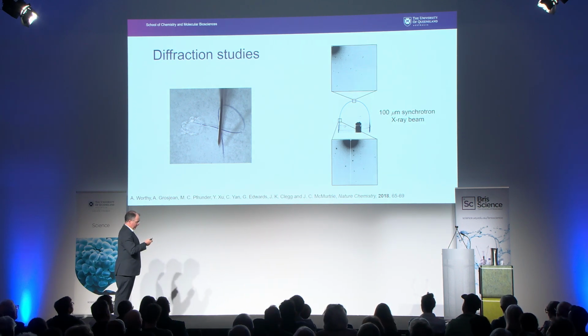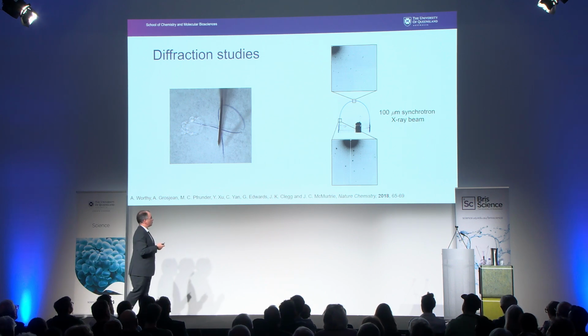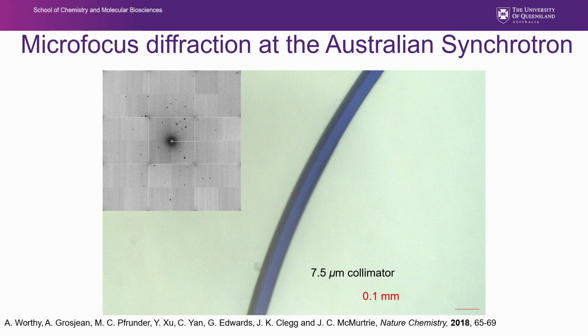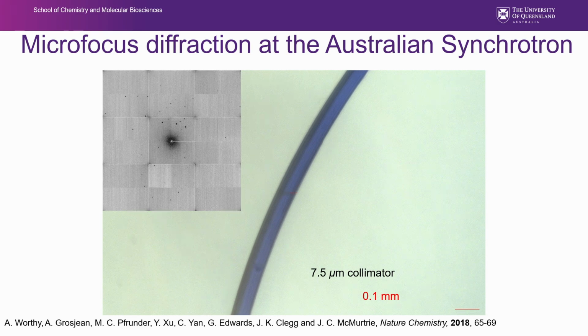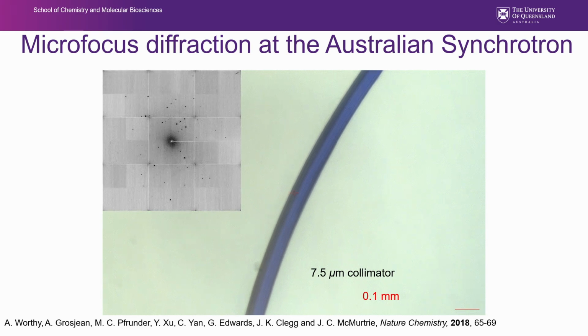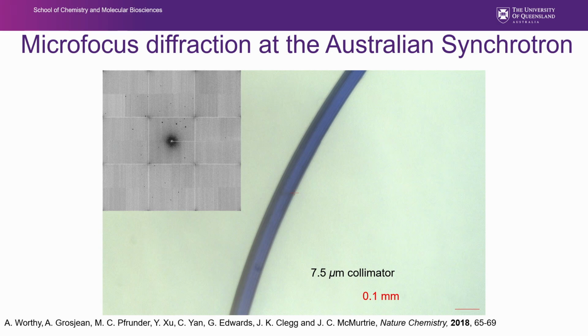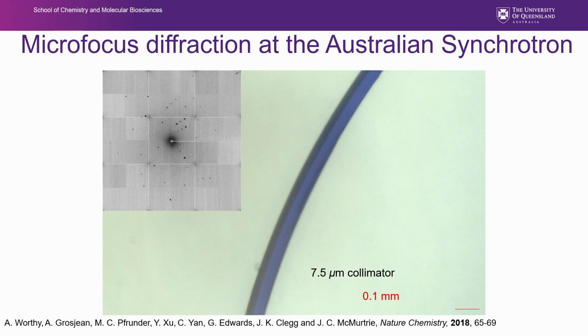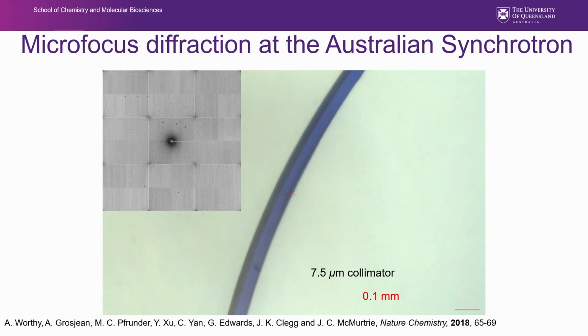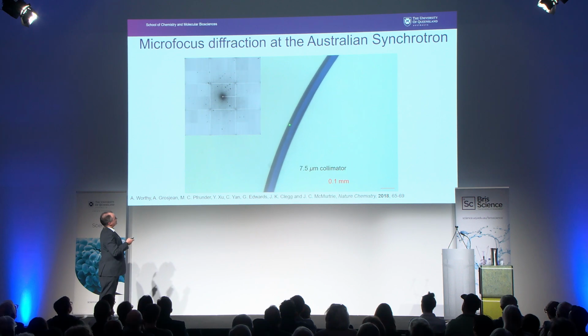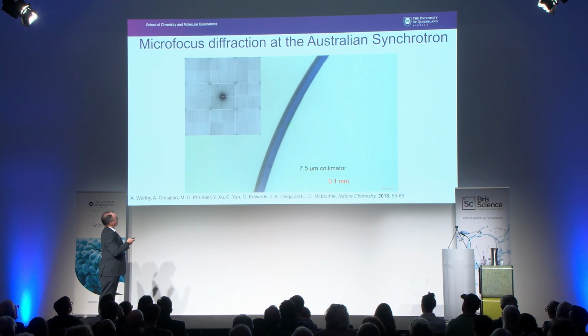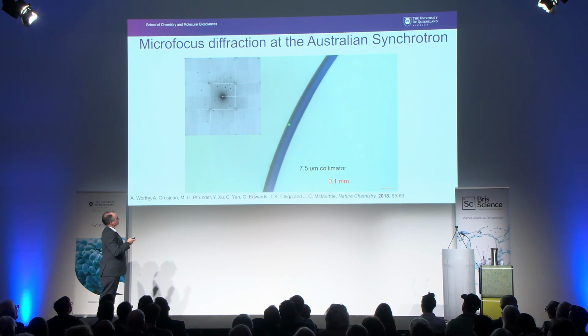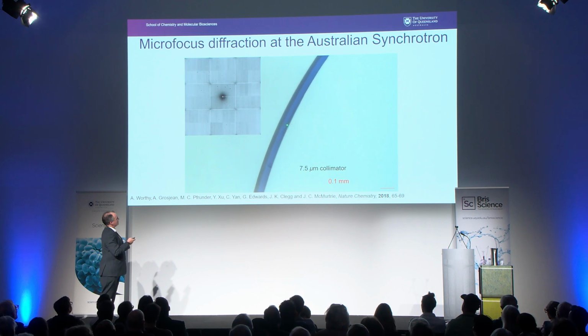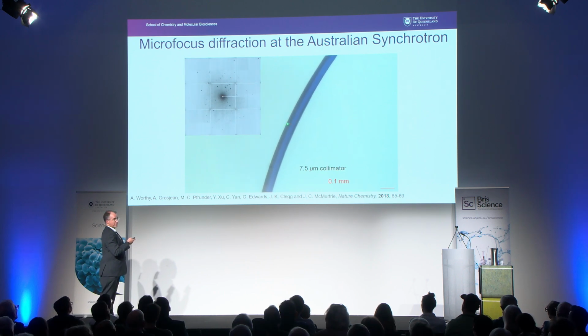We then went to another beamline, also at the Australian synchrotron, where they can focus the beam in a much smaller way. They can focus the beam down to 7.5 microns, so 7.5% of the diameter of the one that we just looked at. And so again, here is our crystal, and this little dot in the center of this axis is probably about the same size as my laser pointer, I suppose, is the size of the X-ray beam.